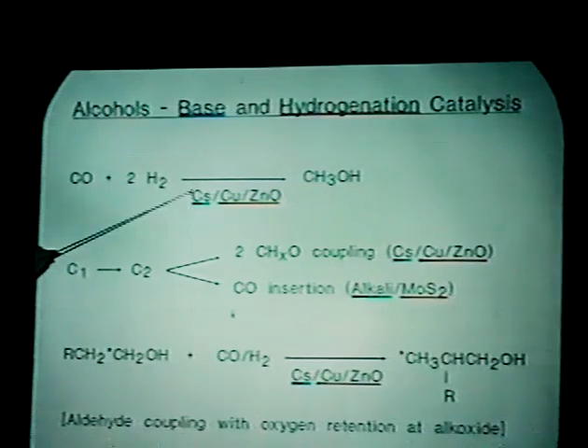If you put sodium in here, you get a mild retardation effect on all these reactions simply because sodium mixes with the catalyst, diffuses inside, and generally busts the catalyst. But not so with these large alkali down to potassium. So in here, we use purely chemical principles. In fact, we know about these reactions that are not at all in any way geometrically or diffusion or mass transport or otherwise controlled. Is there anything that we have discovered in these reactions?